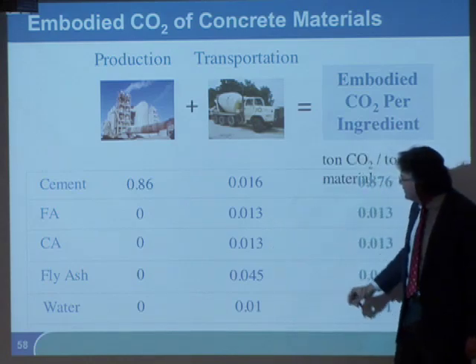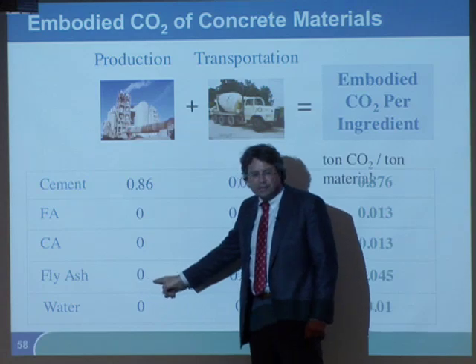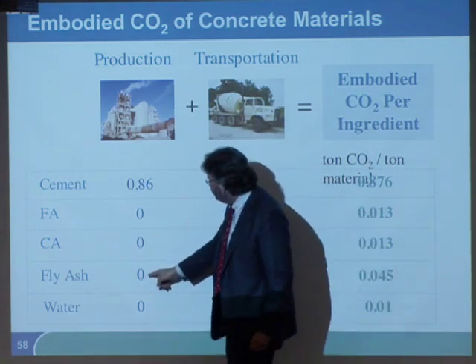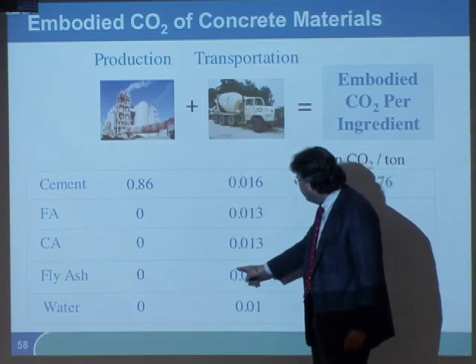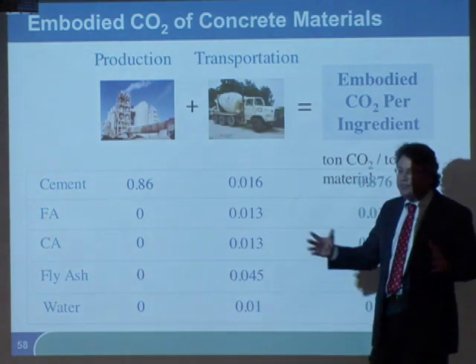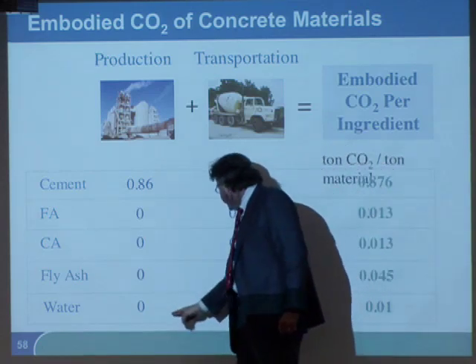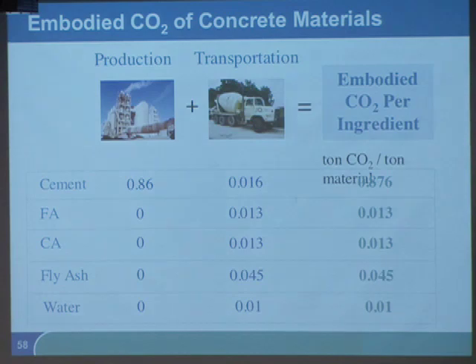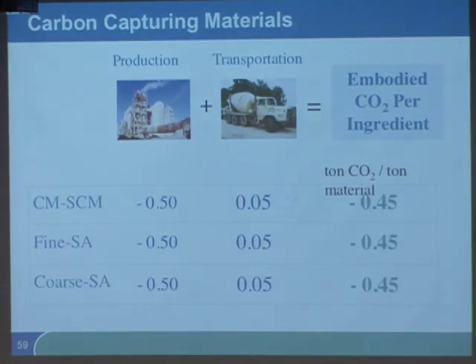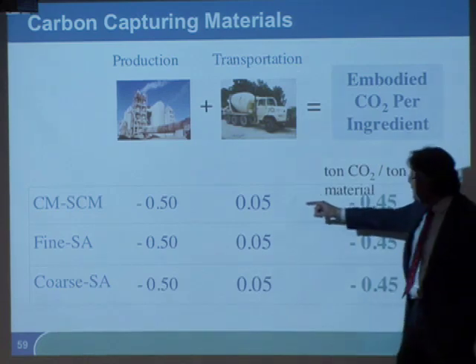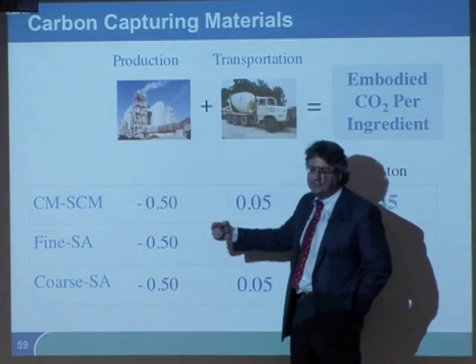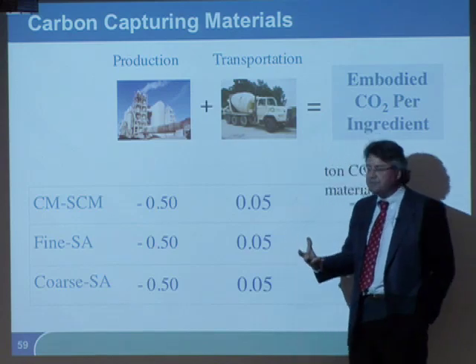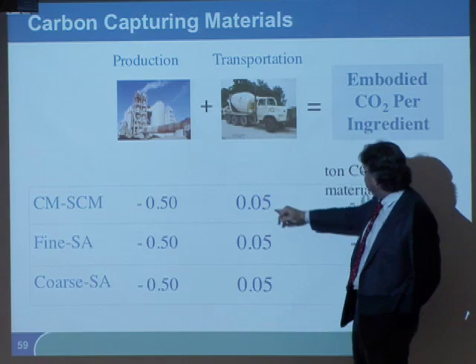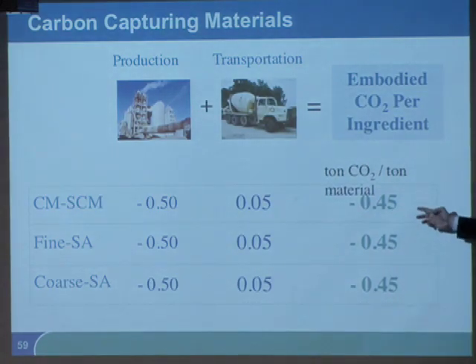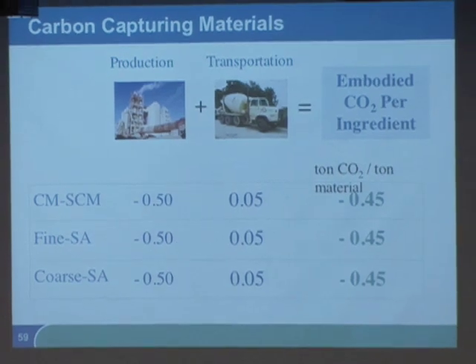Here, there's a carbon footprint with transportation. Since fly ash is used so commonly, we've associated no carbon footprint with that, but a large transportation footprint, because fly ash has to be transported very large distances. And then the water itself has a small carbon footprint associated with it. And then we take the Calera materials. The supplementary cementitious material has half a ton of CO2 in it from the power plant for every ton. We're assuming some carbon footprint associated with transportation. We get negative 0.45 tons. So it's a carbon negative material. And that's true with the sand and the coarse aggregate as well.